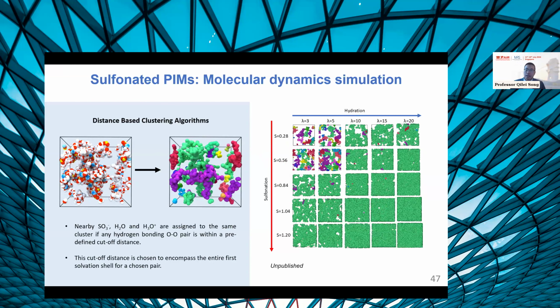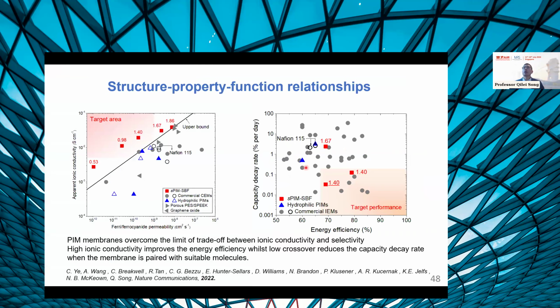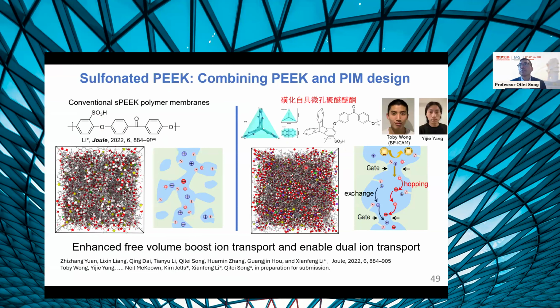So based on this understanding, we extended the design to a new generation of polymers called PEEK. It's a polyether ketone. In the previous study, we collaborated with DICP in China to develop conventional sPEEK membranes and use them in the flow battery device. But the challenge is that these traditional sPEEK polymers, because they're linear, have relatively lower free volume. So when you make these materials into ion exchange membranes, you got relatively low ion conductivity.